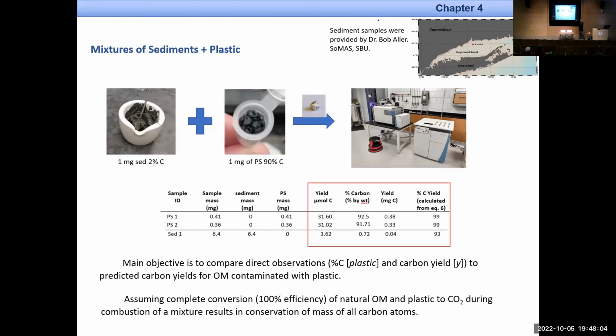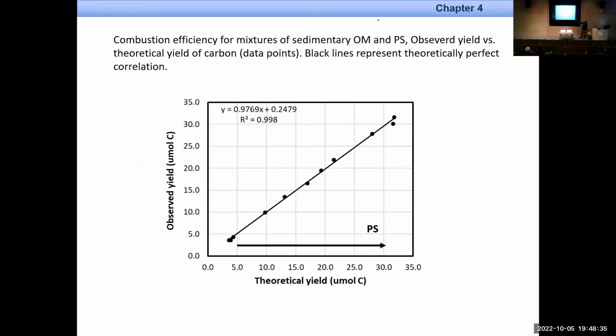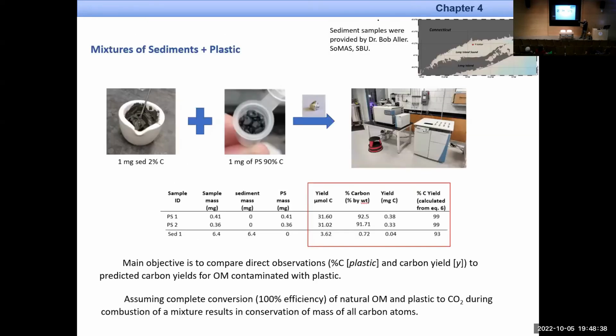And then we put the sample in the elemental analyzer, and it gave us, for example, the percentage of carbon in those samples and the yield percentage. So the idea here is, I know the amount of plastic that I put in those sediments, so I can calculate how much CO2 I should get. I know what I put in, and then theoretically I can calculate what I'm supposed to have. If this experiment follows the theory, I should have the same amount. And that's how I can be sure that the equipment is measuring the plastic in my sample.